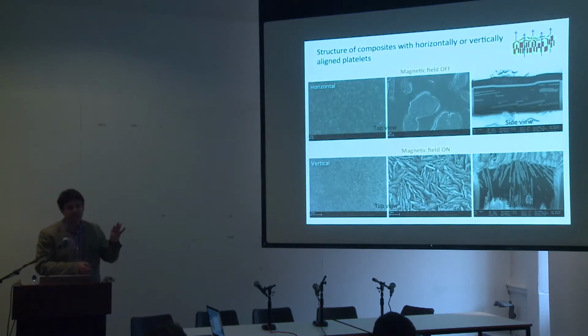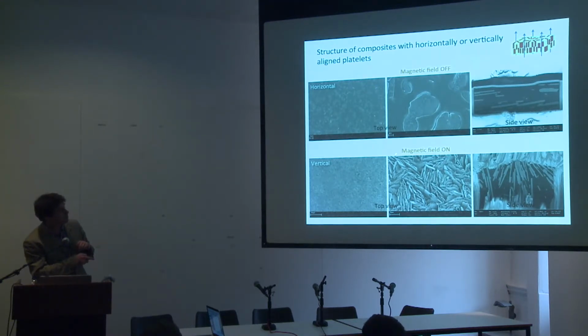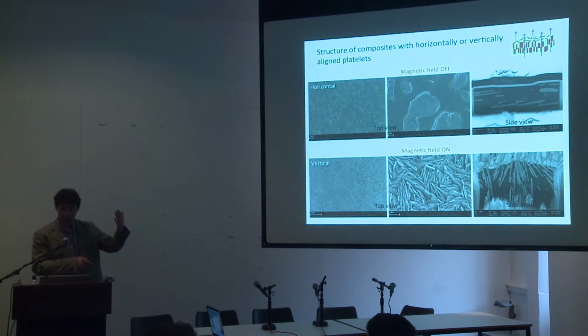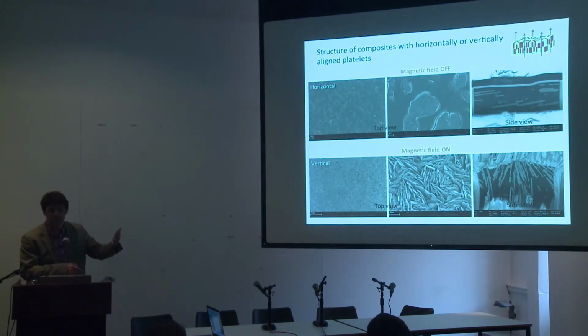So now we have the ability to align particles in a fluid. All we have to do to get a composite is to transform this fluid. So imagine now a polymer melt, or a monomer that you polymerize, to transform this fluid into a solid. Here's an example of one of our first approaches to do that. If we turn the magnetic field on out of the plane, and then we consolidate the fluid, you see that we can nicely keep the orientation that we got through the magnetic field. So in this case, an out-of-plane orientation, as opposed to a horizontal orientation if the field is off.